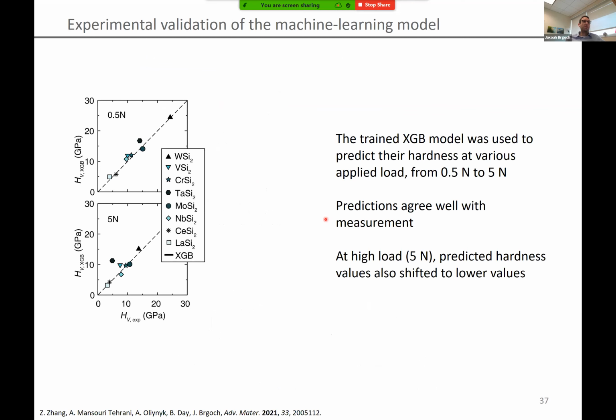Measuring the experimental hardness, here's the hardness measured and here's our extreme gradient boosting prediction. Overall, really good reliability at a half a Newton. It gets a little worse at 5 Newton, but remember we have less data at 5 Newton than at half a Newton.